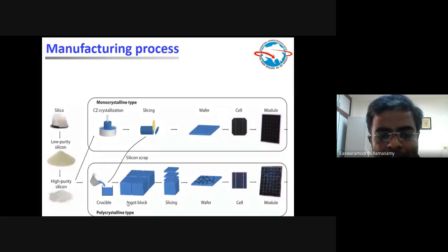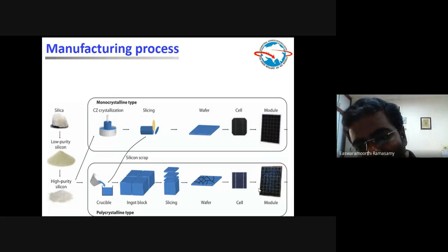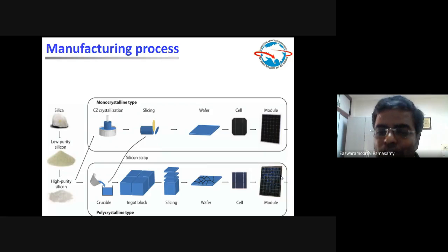For polycrystalline or multicrystalline, it is also the same process. Instead of growing single crystals, here the silicon is melted and cast into a crucible. You will get blocks, and you can slice them. But they are not single crystalline as in the case of the previous approach, so we have polycrystalline. Polycrystalline cells are also doing well, and the efficiency difference between single and polycrystalline is rarely more than 1 to 2% at the cell level.